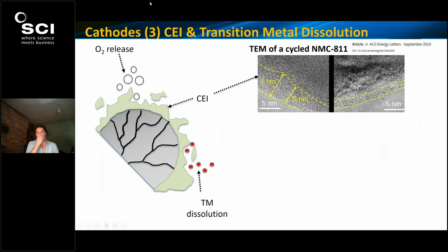So the third, and by no means less significant, aging mode in cathodes, just as we saw earlier, when you first form a battery and you start to passivate the surface of the anode with the solid electrolyte interface layers, something similar happens on the cathode at the higher voltages, where the cathode becomes active. So this is called the cathode electrolyte interface, and we can see a schematic of this, which develops on the surface of the cathode particles because of the higher voltage decomposition of the electrolyte solvents and reaction with lithium compounds.